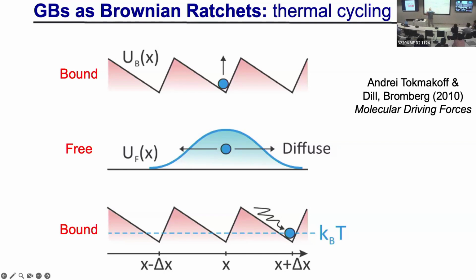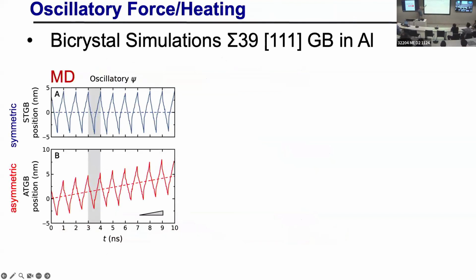Okay. So just to recap, what I tried to show you is for a given grain boundary, if I put on a certain driving force in one direction, it's an asymmetric boundary, it'll migrate faster in one direction than the opposite. I tried to give you an explanation of why that is. And I tried to show you that if I put on an oscillatory force, it'll move net in one direction, or an oscillatory temperature, cyclic annealing. So let's do that in a simulation. If I take a symmetric boundary and I put on an oscillatory driving force, it goes left, right, left, right, left, right, left, right.